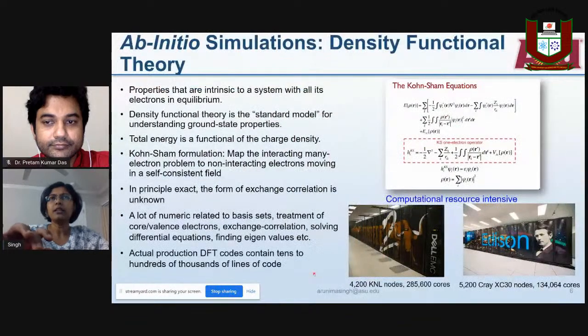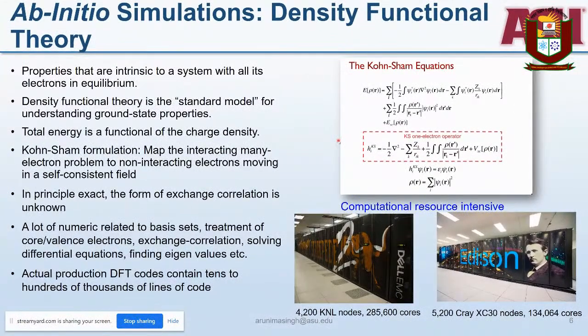So what is that? The so-called density functional theory is an ab initio simulation technique where you solve the Schrodinger equation by using the density functional theory. And this density functional theory is a standard model for understanding the ground state properties. The total energy is taken as a function of the charge density. And the Kohn-Sham formulation, as you see on the right, maps the interacting many-electron problem to non-interacting electrons moving in a self-consistent field. It's a beautiful theory, and in principle it's exact, but unfortunately the form of the exchange correlation functional is unknown. So there are several approximations for the exchange correlation functional, and there are several density functional theory codes one can employ.